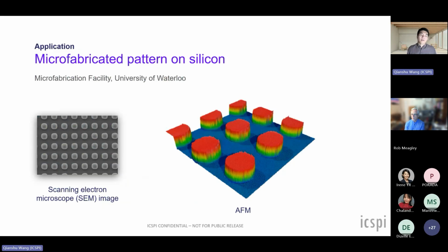This is another example: a microfabricated pattern on silicon, made at the University of Waterloo at a microfabrication facility. On the left, you can see a top-down image taken using a scanning electron microscope. It's a very good image, but we don't really have a good sense of how tall some of these features are. I know that with SEM you can take cross-sectional images, but it can still be challenging for a variety of reasons. AFM has much lower sample requirements, and you're able to get that data fast and easily.